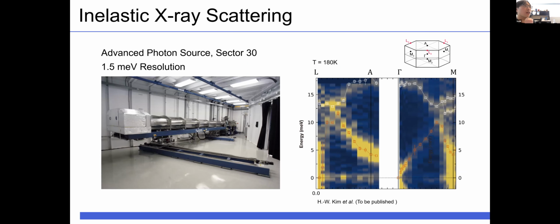So to find evidence of an additional phase transition, we performed inelastic X-ray scattering. We did our experiment at Advanced Photon Source sector 30 with 1.5 milli-electron volt resolution. Although layered materials are easy to bend and generally the domain size is very small, the small spot size of the X-ray makes it possible to follow one grain. The right figure is the phonon dispersion that we measured, and it was very successful.